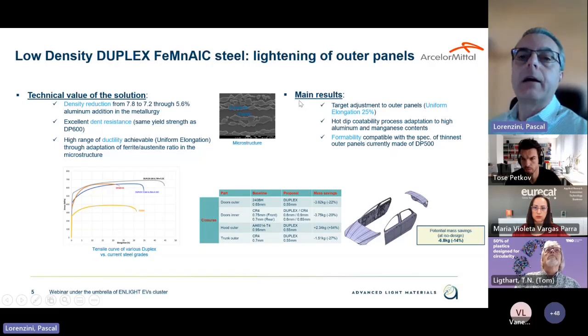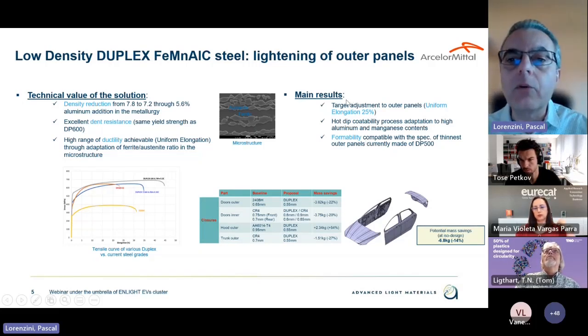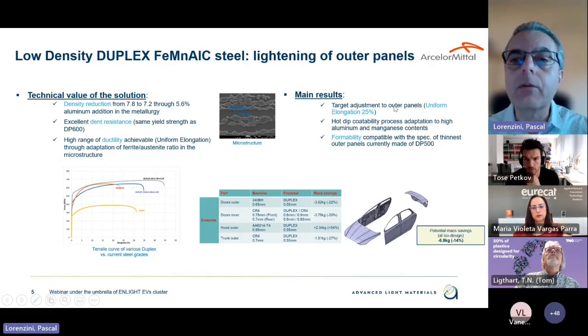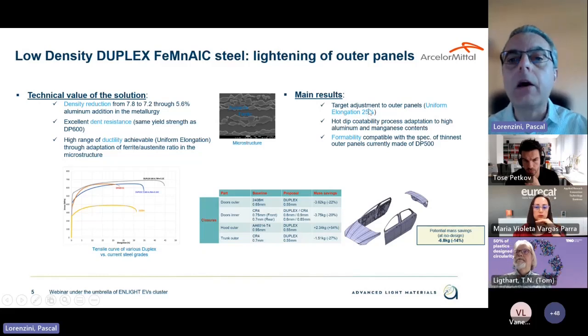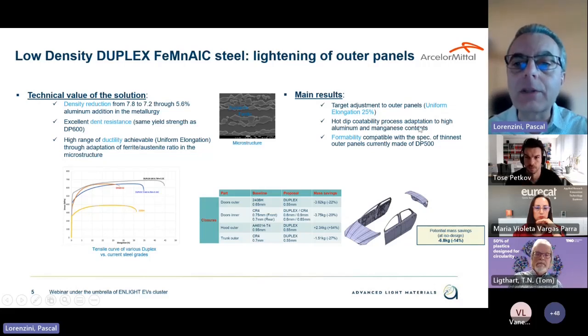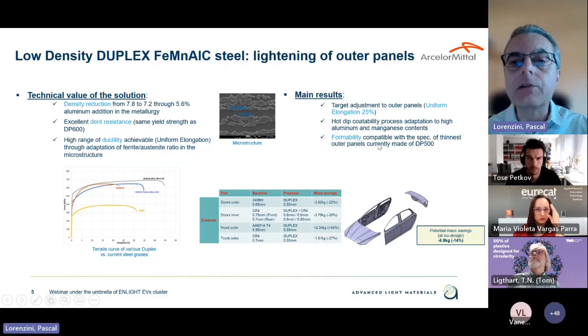concept. And the main results of our involvement in the project are, on the one hand, the adjustment of the target to the spec of the outer panels in terms of uniform elongation to be reached. The adaptation of the hot dip coatability process to the high aluminium and manganese contents of this kind of steel. And the verification of formability, which is compatible with the specification of today's thinnest outer panels made in the best in class steel grade for this kind of use, which is Dual Phase 500.